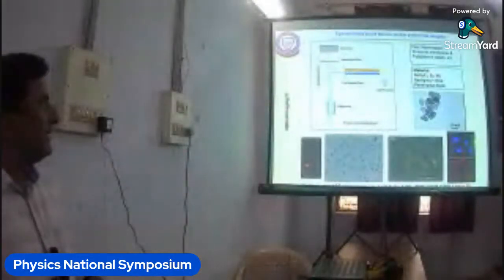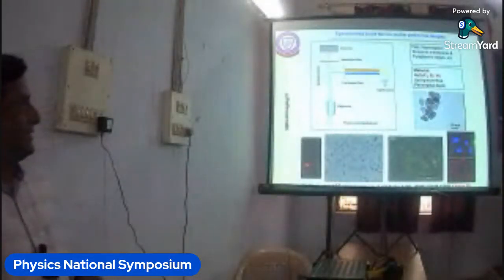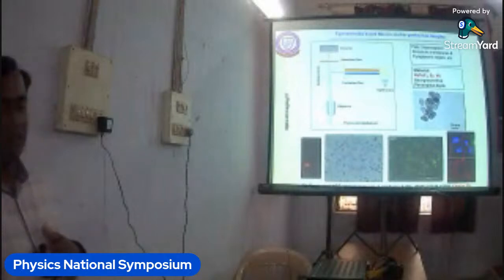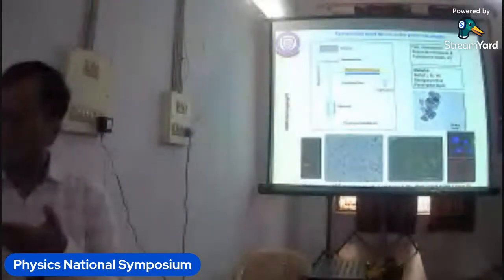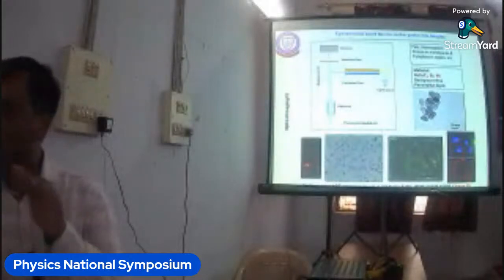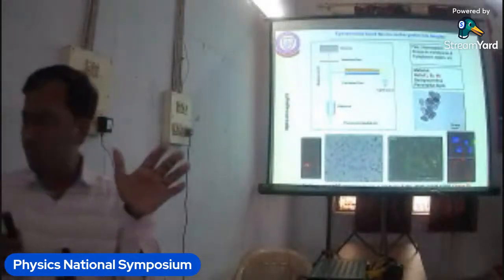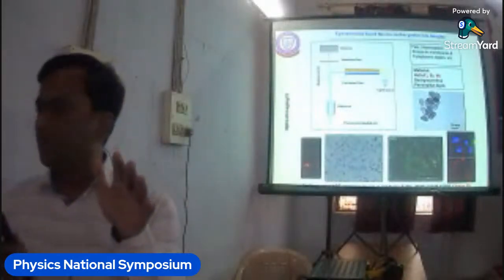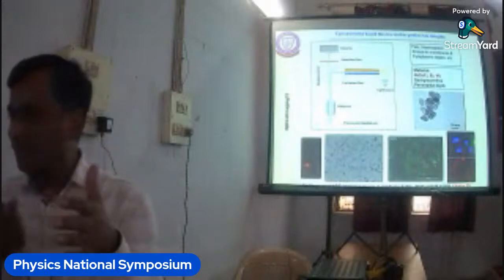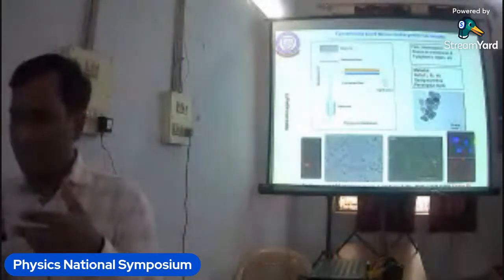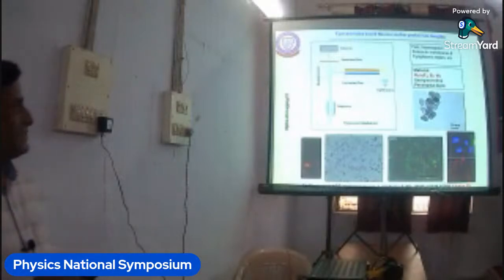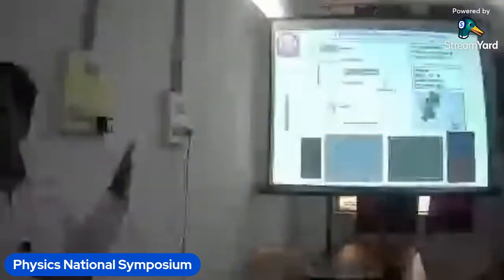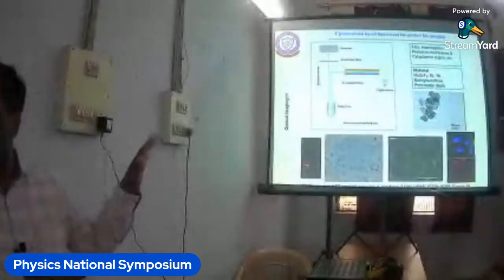Okay. So what we did, we synthesized a system of sodium scandium fluoride. Why fluoride? Because fluoride can be synthesized in a liquid form. If you are targeting any biological application, then you must have your sample in liquid form. Then only you can inject it inside the body. So we synthesized sodium scandium fluoride. Activator was same, erbium and Yb.